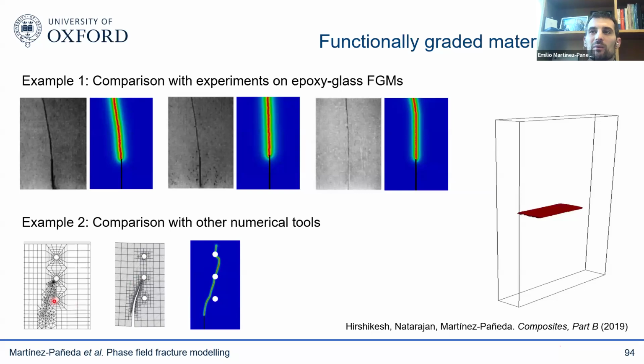This is a 3-point bending experiment with these classic holes. It goes to the second hole, but it initiates again, and then goes to the third hole, and then initiates again from the top of the third hole, and you get the complete failure of the sample, which is something that all the methods based on remeshing, XFEM, and so on are unable to predict.